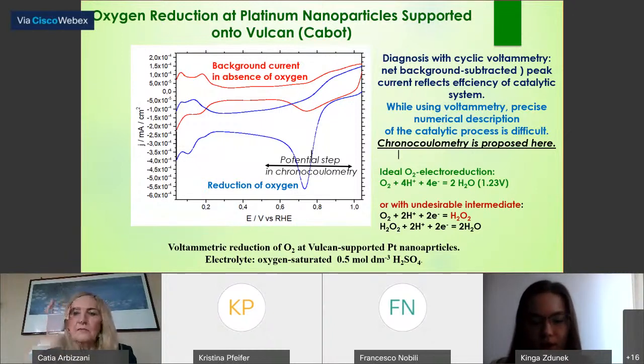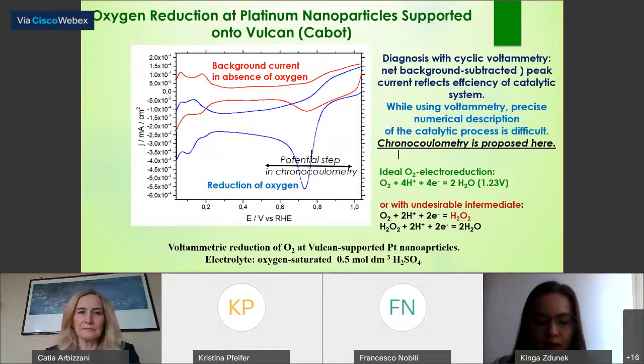Because while using voltammetry, precise numerical description of the catalytic process is difficult, we propose chronocoulometry here. The reduction of oxygen takes place on the metallic platinum, which is formed as a result of the reduction of platinum oxide. I applied a pulse between 1 volt and 0.5 volts and studied the process of oxygen reduction with chronocoulometry.